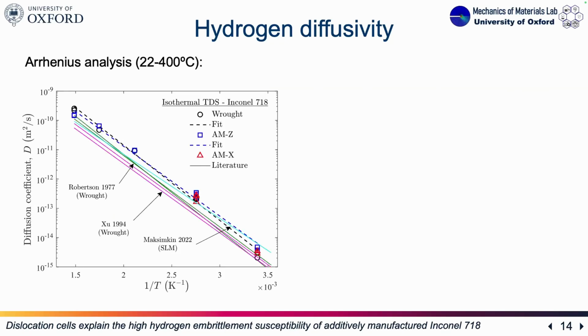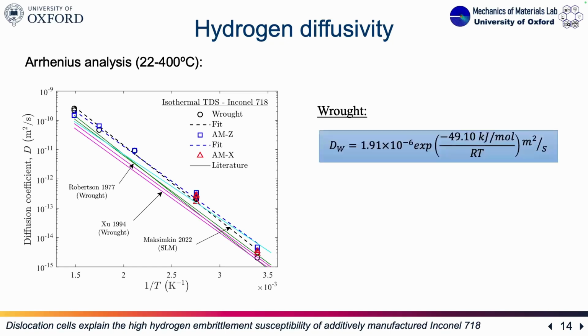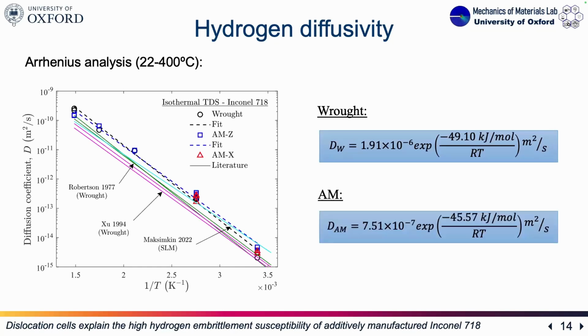So if we have data for diffusivity at a wide range of temperatures, we can do an Arrhenius fitting, and we can determine the Arrhenius law. All right, which is really interesting if we want to have the diffusivity at any temperature, and also to compare our data with the previous data found in the literature. We see a quite nice agreement with what we've seen so far in the literature, and we have determined this Arrhenius relationship for both the wrought and the AM.